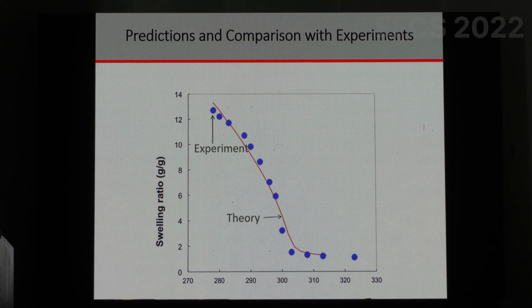So we started looking at this model, and so here is, after a lot of work, and skipping all of that work, the comparison between experimental data, which is the swelling of the polymer gel as a function of temperature. And you can see that the polymer is nicely swollen at low temperature, and then it suddenly collapses at high temperatures. So this is the volume phase transition, and the theory does a very good job of fitting the experimental data quite well.